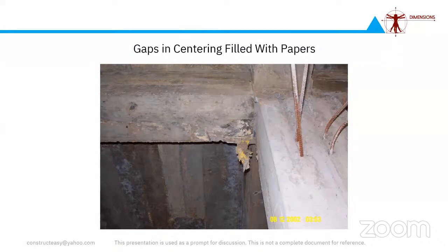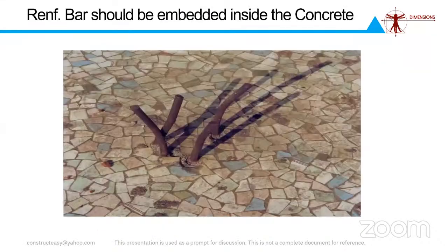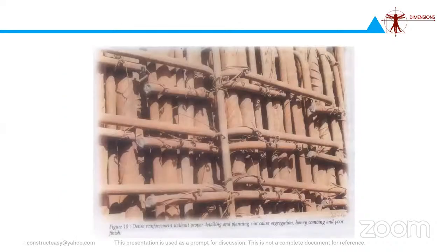This is probably paper which was used for filling the gap. And there are portions of the reinforcement from columns or any element left exposed to the atmosphere. This is again an ideal situation for corrosion to set in, because the steel bar is partially inside a highly alkaline medium, concrete, and partially outside. It is exposed to the humidity, and therefore the corrosion starts very early.